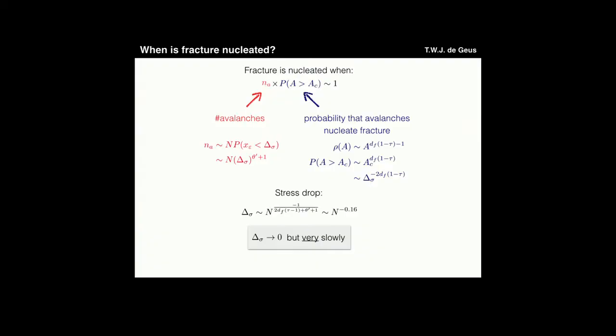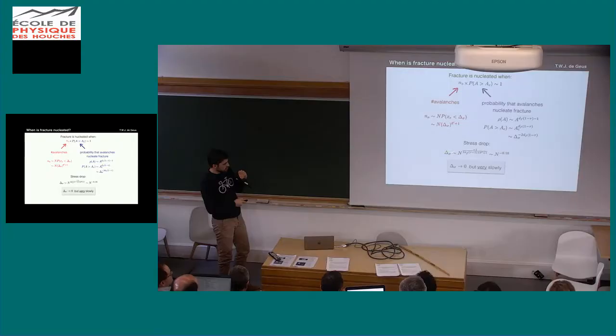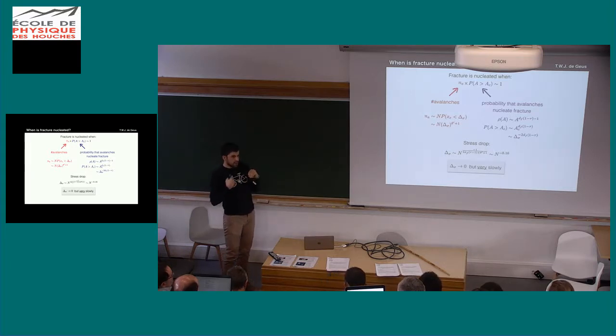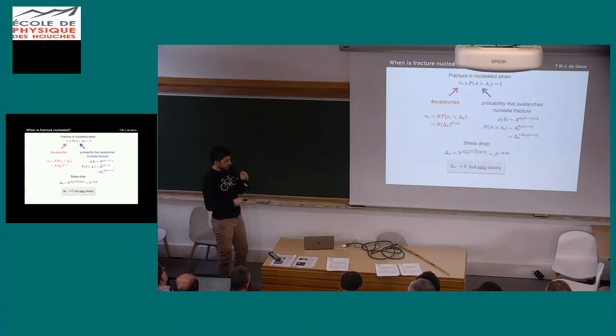And when we put this together, we get an expression for the typical stress drop as a function of system size, so number of blocks. And we see that the stress drop decreases with increasing system size. So in the infinite limit, in an infinite system, the stress drop will be zero. So stick slip friction will disappear, or hysteresis in the pinning will disappear. However, it does so very, very slowly.